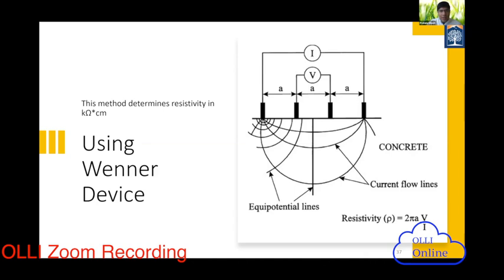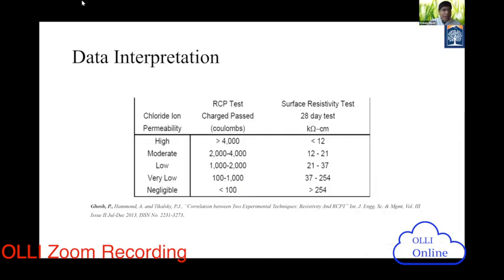So now we see how the testing parameters are done. Again, I'm not going into details of how testings are done, and we are just interpreting with the charge pass. Remember, the charge pass is the indirect indication of the corrosion propensity. So if you have high charge pass from any concrete like 4,000 coulombs, then it's a really bad concrete. Original concrete, those who are just using ordinary Portland cement, generally goes through like 3,000 to 4,000 coulombs, which is really bad. High chloride ion permeability because charge pass is so high.